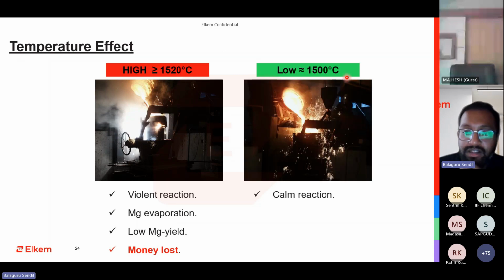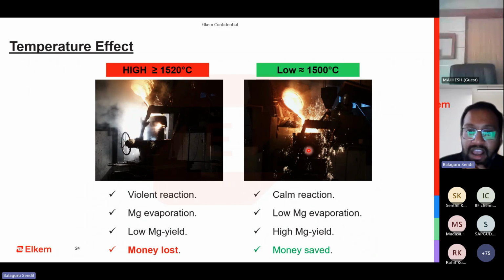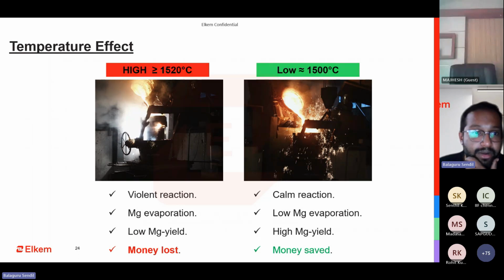So if you look at it, these are the test condition images. So you see here, this is much more violent. This is a much calmer reaction. So you have low magnesium evaporation, that is, fume generation is not very high. If you see a lot of fumes, you see a lot of magnesium being wasted. And the magnesium yield is always higher. When the yield is higher, the consumption is lower, and you save money. Additionally, a 20 to 25 degree saving in your superheating temperature directly saves money. So this is the impact of having a correct temperature.